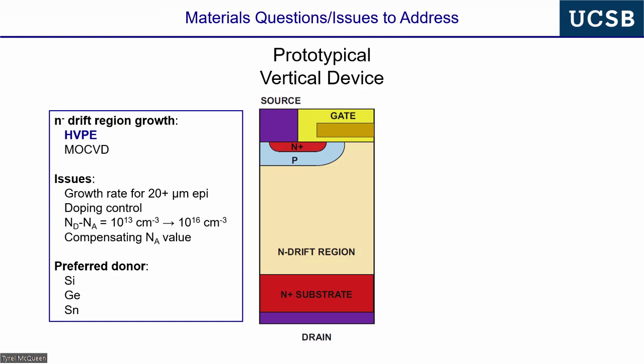We would like to have high growth rate MOCVD. Both of these are frontier areas in our research, but we need to have sufficiently high growth rate that it's meaningful both for how many hours as students you're willing to spend in the lab growing a crystal, okay? And then it's also economically feasible. HVPE growth rates can be astoundingly fast. Typically, when you think about MOCVD or molecular beam epitaxy, you think about growth rates of, say, a micron an hour or a few microns an hour. But HVPE growth rates can be tens to even hundreds of microns an hour, okay?